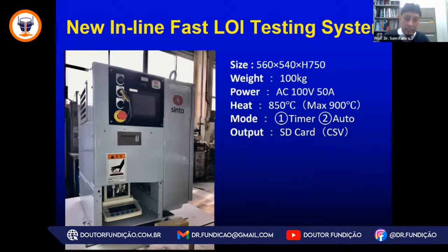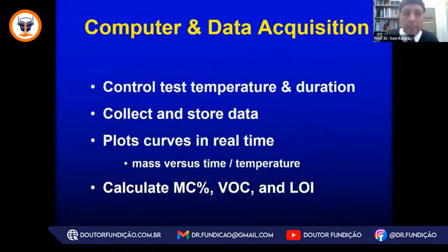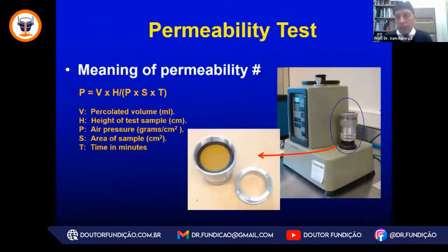This technology is available for working foundries, and it uses computer data acquisition to control test temperature and duration, to collect and store the data. It plots the curves for mass loss versus time and temperature on the sand, and calculates the moisture content, the volatile chemicals, as well as the loss on ignition in a chemically bonded sand. And again, this type of data can be achieved very quickly today.